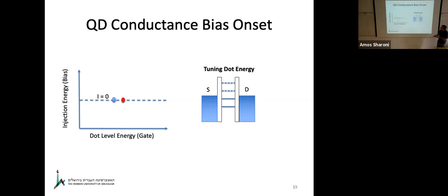Now, you can do the same thing with bias. You start applying bias and you reach this level. But now you have to remember something important. All these source and drain electrodes have huge capacitances of their own, so the energy is going to run away from you. If you calculate everything correctly, you're going to find that there is a condition where the source catches up with this available resonant level. And that means that, of course, if you apply positive bias, it means negative energy. And again, you have an onset condition of current. And you can easily show that there is a diagonal, which is an onset condition where this resonant level is resonant with the source. We call this the source onset condition. This is a condition where the source catches up with the available energy level.